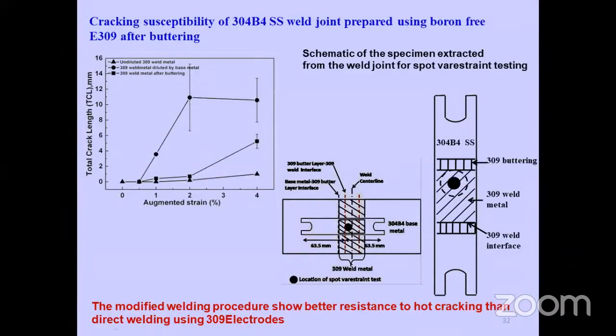We prepared weld joints by using this method, and again we have extracted specimens. This is the weld joint top view. Here we have made a buttering from both the sides using 309 electrode, and again we joined it using the same electrode, and we have extracted the specimen from the weld joint, and we have tested the spot varestraint using spot varestraint experiments in this region where base metal dilution is expected in the buttering zone.